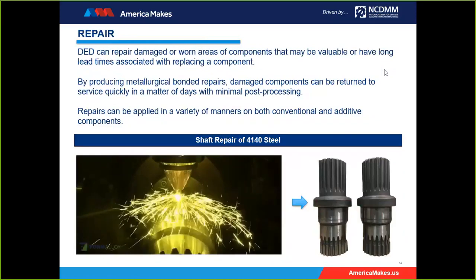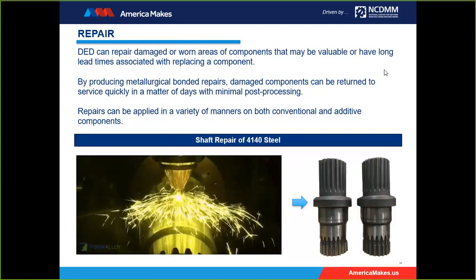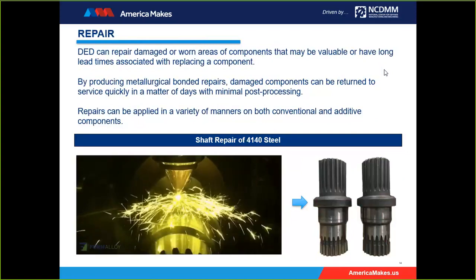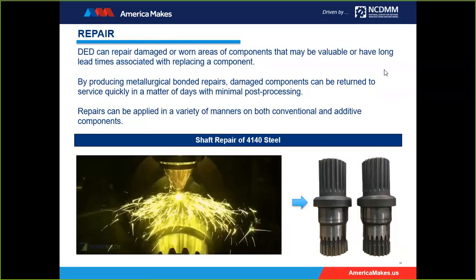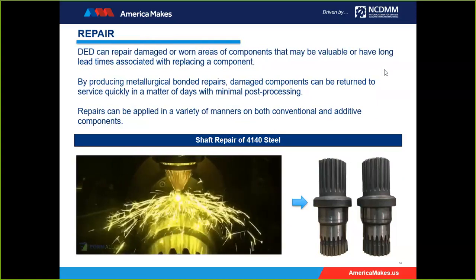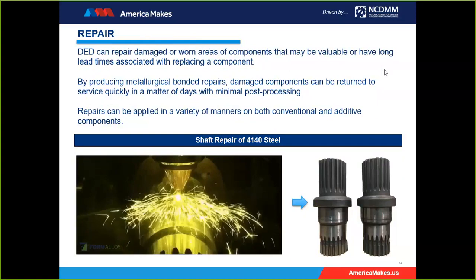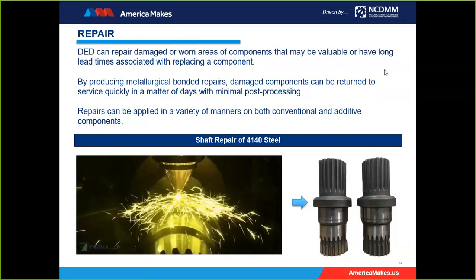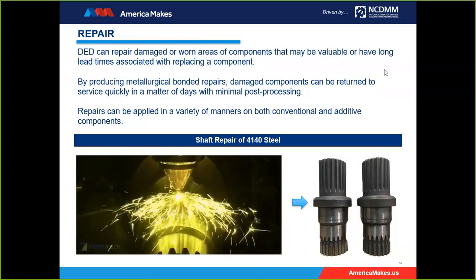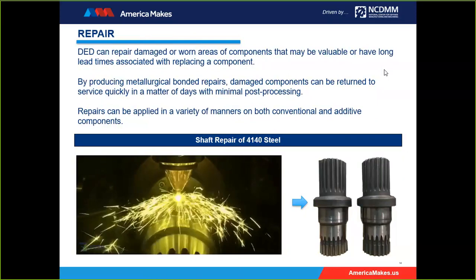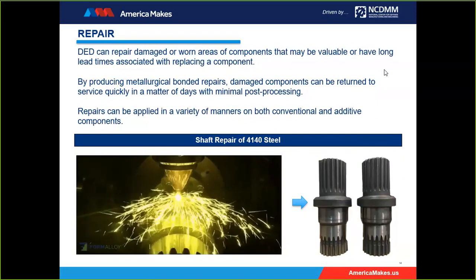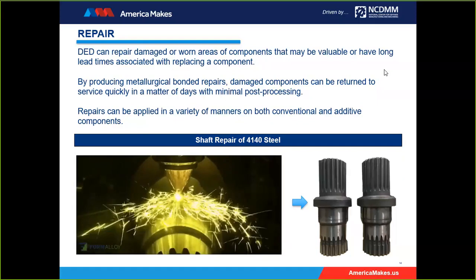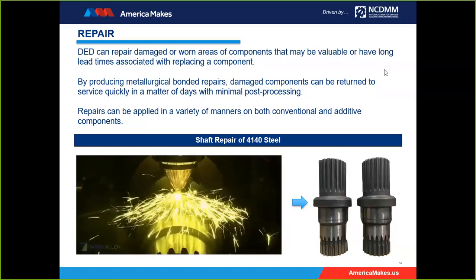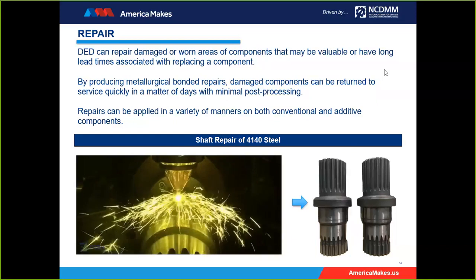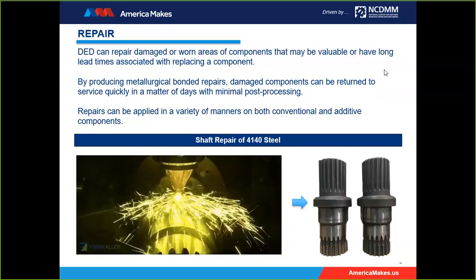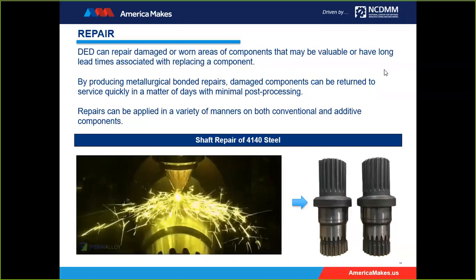DED has been around to repair damaged and worn areas of components for decades also. This can be crucial to returning a system to operation if a damaged part has a high cost for a replacement or long lead times associated with it. By cutting down the lead times to potentially days and returning or extending the life of the component, the capabilities of DED repair can be invaluable for those in both additive or subtractive components. Below is an example of a locomotive shaft repair that we did. By reapplying material back onto the shaft, we were able to return it to service within the week.